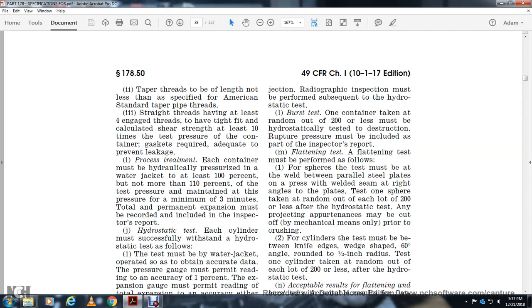The burst test. One container taken at random out of 200 or less must be hydrostatic tested. The destruction rupture pressure must be included as part of the inspector's report.